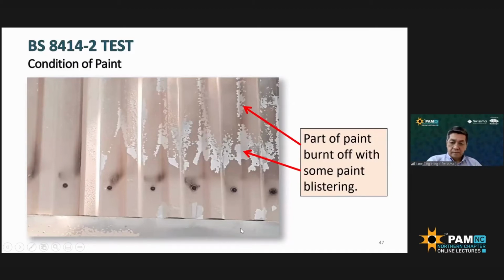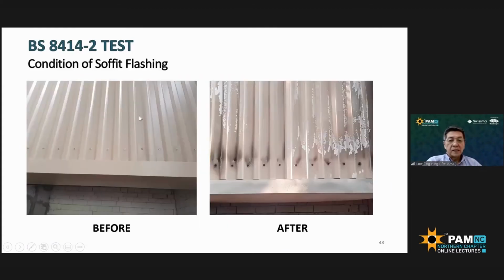So this is flashing above the combustion chamber, and you can see that the paint has been burned in some areas, and there is blistering of the paint in other areas. The self-tapping screws are still intact. Could be just burned. It didn't fall off or rupture. So this is before, and that's after.